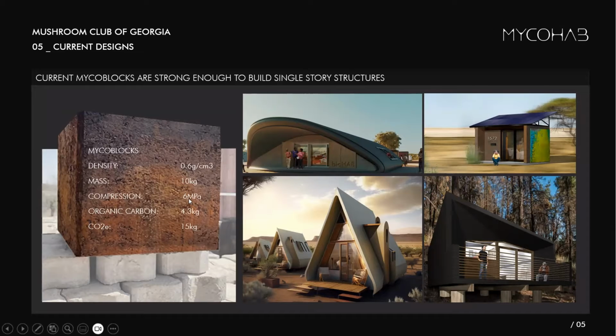The compression strength, we're getting about 6 megapascals in Namibia. And that is pretty much comparable to the strength of concrete blocks in Namibia. They're closer to about 7 megapascals, but this is much stronger than earth construction or earth block construction, which is commonly done in this area. And the burnt bricks in Namibia are actually much weaker too, so they would be under that 6 megapascals. We've been able to get up to 26 megapascals with our work here in Cleveland, and I'll show you some of that work later. But the rate limiting factor is our presses. The press that we use in Namibia, we built ourselves, or we had built in country, and it works well for what we need there. But to get to a much stronger material, we would need more powerful and bigger presses to do that.